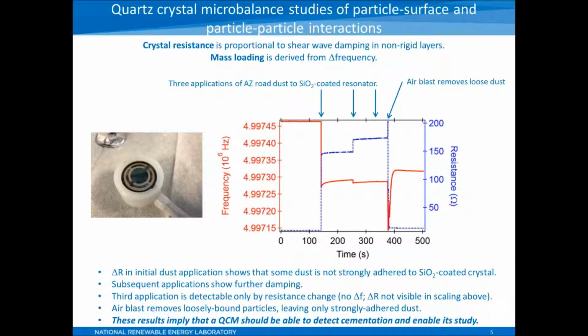This graph is one of the very first sets of data that I took with the instrument, and it's a relatively crude experiment. I simply dipped a Q-tip into a bucket of Arizona road dust that was sitting in our cabinet. This is a standard material that you can buy from a number of different vendors, and then just flicked it onto the surface of the crystal. So what you see there after 2 minutes or so is what you would expect, at least in a fairly naive interpretation.